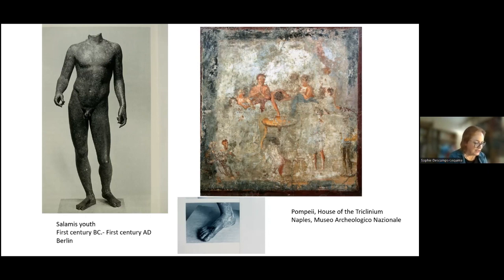and this state would have led to a change in taste, dictated by the new aesthetic that the inevitable darkening of metal surfaces imposed. This phenomenon may explain the appearance before the end of the Hellenistic period of intentionally dark artificial patinas, as observed by, this was his hypothesis, Professor Halma in 1994 on the Salamis youth. And you have a fresco from Pompeii in the so-called Triclinium house, dated between 50 and 79, featuring a very dark, smaller than life-size figure resting on a circular plinth. This is indeed a statue whose metallic skin reflects the light.